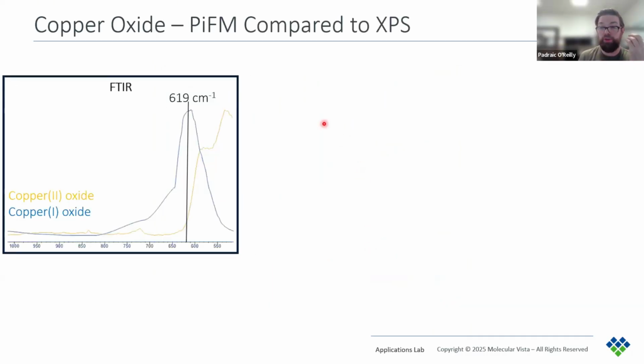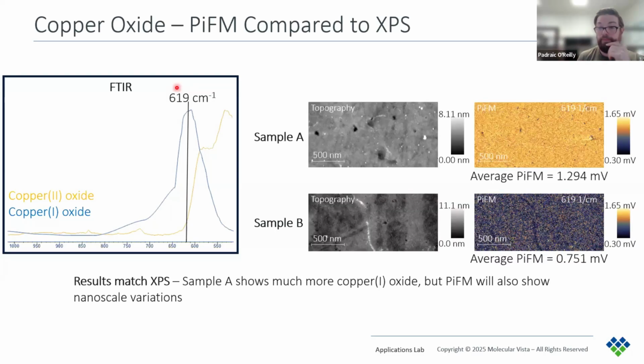So for PiFM, we can use the FTIR of these oxides as references. Copper-1 oxide shows a strong peak around 620 or 619, as it's highlighted here. So we can use this wave number for imaging the sample. Here on the right side, we have the PiFM images. So these are the chemical images, which are at 619 and therefore highlighting copper-1 oxide. And it's clear from these that sample A is showing a much stronger signal than sample B is. And this matches what the XPS showed.